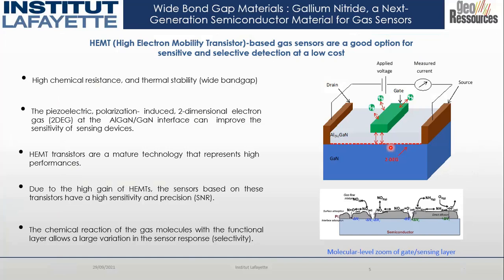Now, the question could arise why we choose this specific GaN material and HEMT structure. A HEMT device is formed with an aluminum gallium nitride and gallium nitride epitaxial growth. This combination of high band gap and low band gap material creates charges in the channel of the device. When we apply voltage between the source and the drain, we get the movement of this charge in the form of output current that we can measure. This device is a surface activated device. Any change in the surface state can modulate the charge in the channel with a high gain compared to other conventional semiconductor gas sensors. So the device can detect gas with high selectivity and precision. This is how our device works. Thanks to the properties of gallium nitride, because of the high band gap, it provides high chemical resistance and thermal stability.